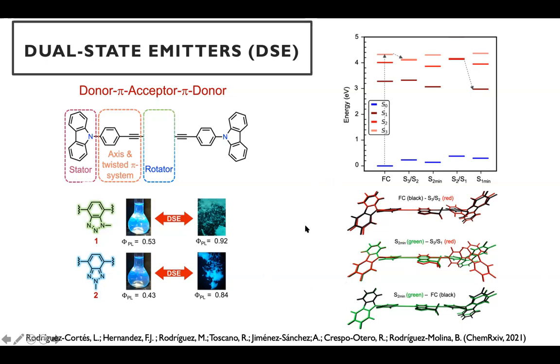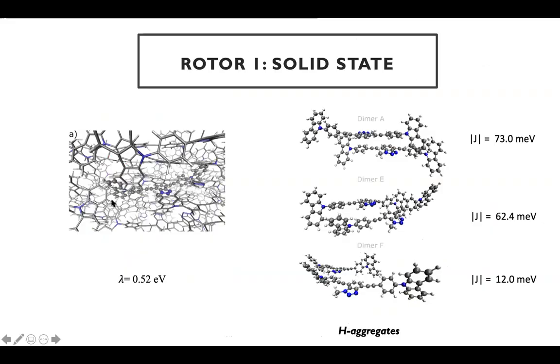So in some of these systems, in practical terms, when you move to media with high viscosity, you can see two emission bands. We also calculated the solids here, and you can see that you have significant reorganization energies. You have values of exciton couplings that in this case, because of the more effective interaction between the central parts of the systems, are a little bit higher, but still won't allow a more effective transport regime for this kind of system.